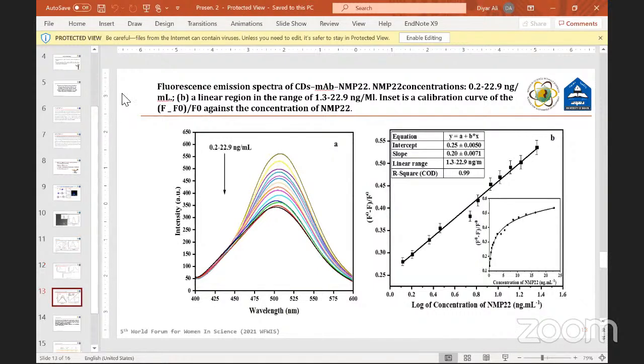For the calibration, we used different concentrations of NMP, and we started from 0.2 to 22.9 nanogram per ml. We can see that with increasing concentration of protein, the fluorescence is quenched gradually. And we have the calibration curve for it, for which we get an R square of 0.99, which is a very good result. We can depend on it in the future.